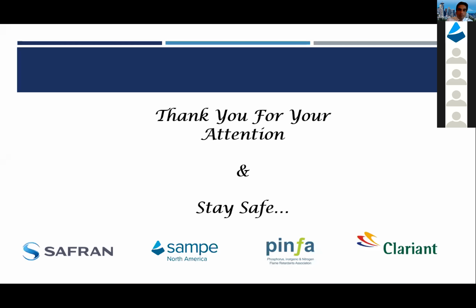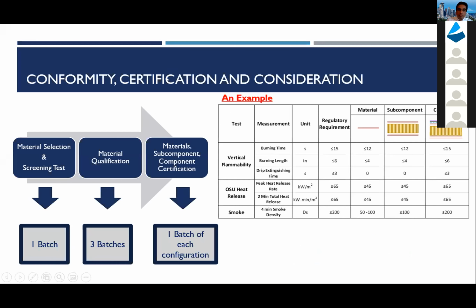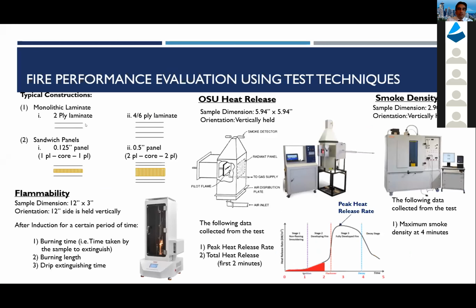Okay, I'd like to go back to the particular slide. If you see, the constructions used are 2-ply laminate and 4 to 6 ply laminate. A 2-ply laminate is the worst case scenario. It catches fire very quickly and burns very fast. That's why we consider the thin laminate the worst case scenario, whereas 4 to 6 plies are quite common in the application. That's why we use monolithic laminate construction this way.